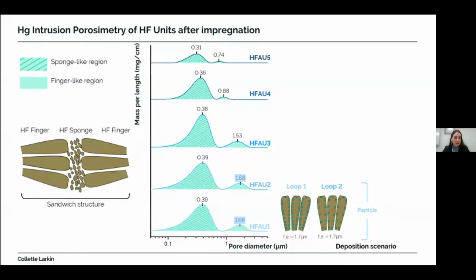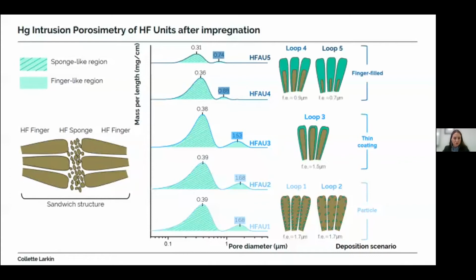After 3 impregnation loops, the pore size distributions of the finger-like region shifted to the left marginally without a decreased intensity of the peak. And this suggested that a thin coating of calcium oxide covered the entire inner surface area of the fingers. Whereas after 4 and 5 impregnation loops, the pore size distribution shifted to the left considerably and decreased in intensity. So this suggested that the inner surface area of the fingers was covered entirely by a layer of calcium oxide that was so thick it filled the fingers.